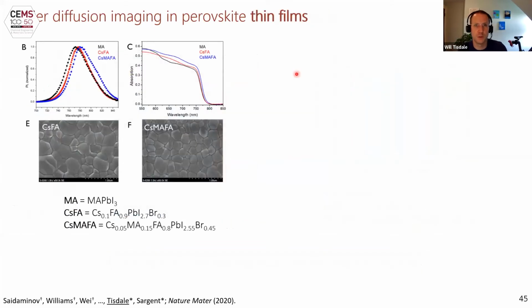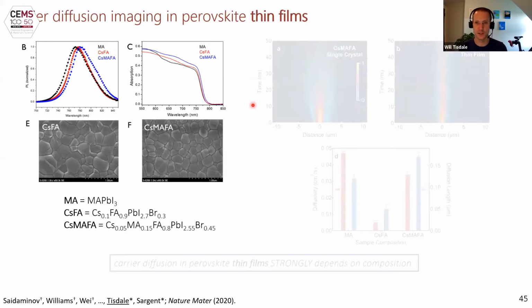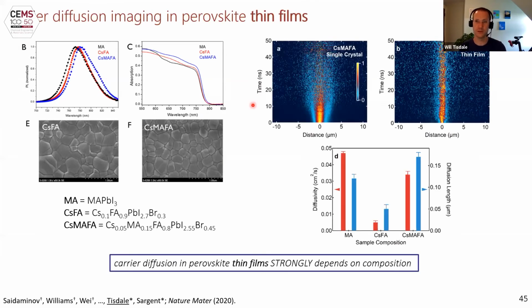Well, this is because you don't make solar cells out of single crystals. You make solar cells out of thin films. And the thin films are not single crystalline, they're polycrystalline. The size of these domains is about 100 nanometers or so. And when we did the same carrier diffusion imaging experiments on these polycrystalline samples, we saw much larger variation in